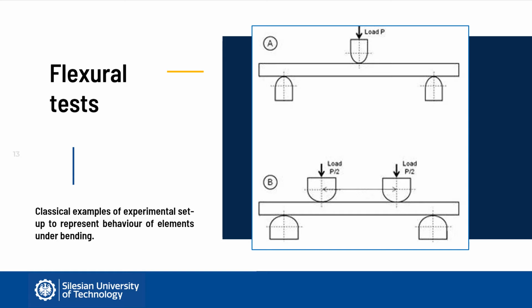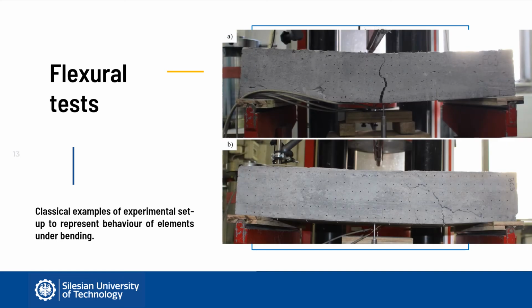We know that the mode of work of such elements will be governed by either bending or by shear. This will depend on a number of parameters such as the depth to effective span ratio or related to the applied longitudinal and transverse reinforcement. The mode of work will be manifested by the mode of failure, which we can distinguish by formation of either a splitting crack in the span or a shear crack near the support.